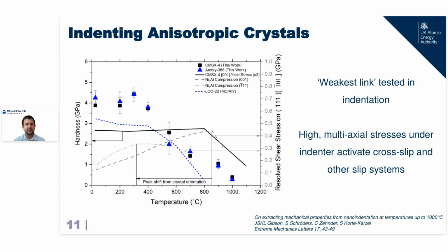Those literature data where we see strength up to 800 come from tensile testing a 001 oriented single crystal. So you're only activating a specific set of slip systems. Actually, when you've got a nanoindenter, you've got a much more complicated stress state. You've got this hemispherical zone of plastic deformation under your indenter tip. You're activating all your available slip systems. You've got very high stresses, and so your dislocations can cross slip. And so what you get, in fact, is cross slip and deformation on much softer crystal slip systems.